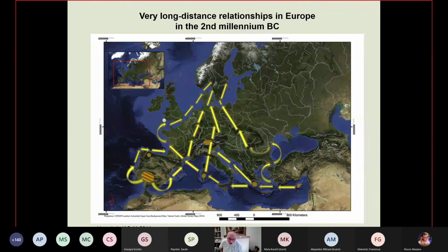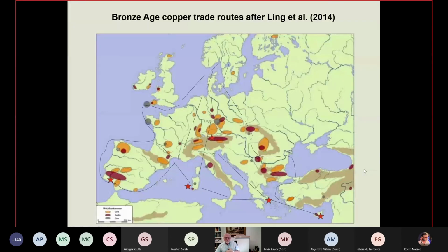So if you look at all the Mediterranean data, you do find some matching lead isotope ratios, and then you say, okay, we have copper from Cyprus and from Ireland and from Sardinia and southern Spain in southern Sweden. Well, this overlooks the fact that we have many more copper deposits, very large ones, as I have shown in Mitterberg, in Central Europe, which were not included in this comparison.